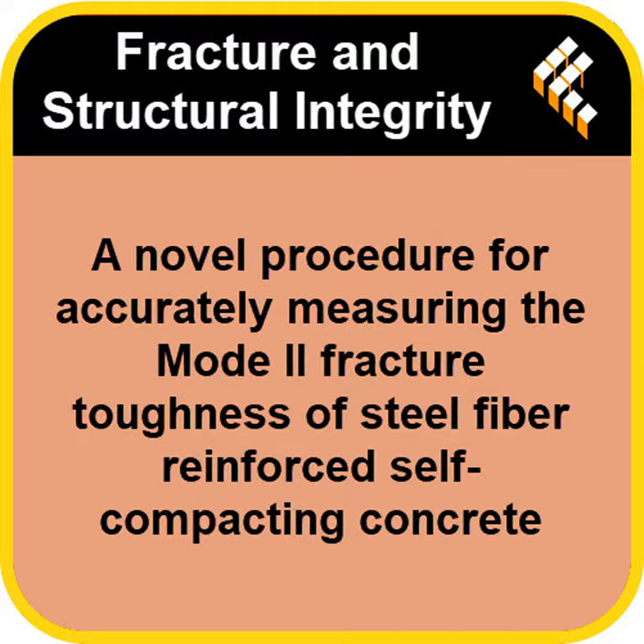You have to talk about how they made those Mode II cracks. You mentioned it preserves the bridging. How? It's pretty ingenious, actually. Instead of cutting, they inserted thin foam panels, just 2 millimeters thick, into the mold right where they wanted the crack to be. Foam panels? Inside the concrete mold? Yep. And here's the clever bit. They actually glued some of the steel fibers directly onto these foam panels before pouring the concrete.